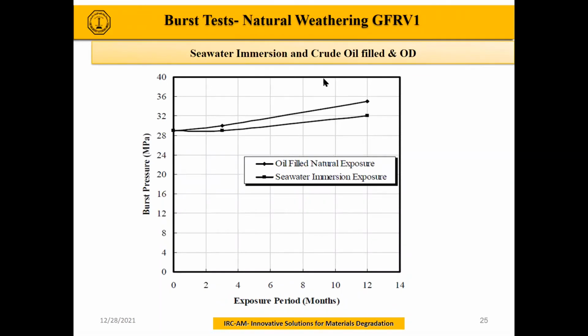The burst test showed almost the same trend also for GFR-V1. You can see after up to 12 months, the burst pressure has increased also, and that is due to the fact that we have more cross-linking, the material has cured under the exposure.